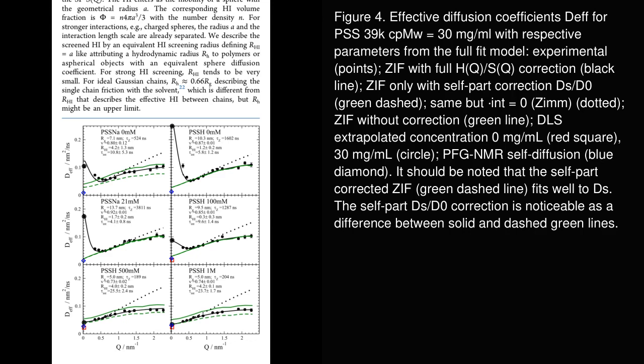Furthermore, the hydrodynamic interaction screening radius, RHI, inferred from fits, varies with salt concentration, being lowest at intermediate salt but larger at very low and very high salt. This behavior matches changes in polymer charge and counter-ion adsorption, impacting interchain coupling. Overall, Figure 4 quantifies the nuanced interplay of hydrodynamic interactions, electrostatic screening, and internal friction that dictate polymer diffusion dynamics across length scales.